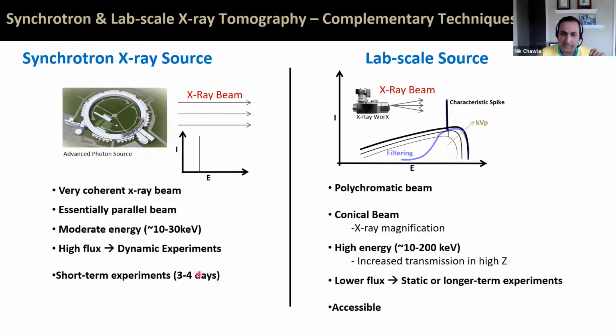In the lab, we have a polychromatic beam. So it's kind of a conical beam with multiple energies. And so we'll do filtration in the synchrotron too, but we definitely do filtering in the lab source so we can actually get to a range of energies that are of interest. We can get up to almost 200 keV, so we can do very high Z materials, things like tungsten, things like steel. But we overall have lower flux than what you do at the synchrotron, 3 or 4 orders of magnitude lower.